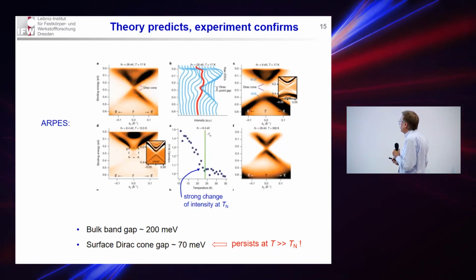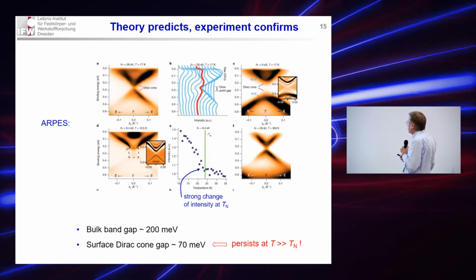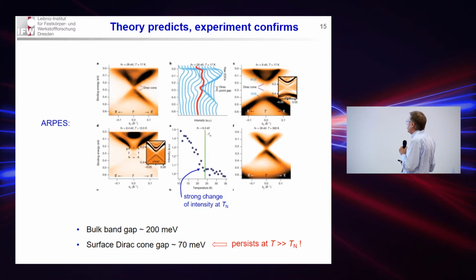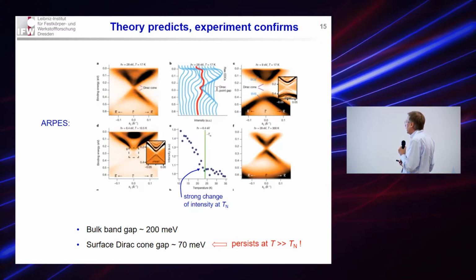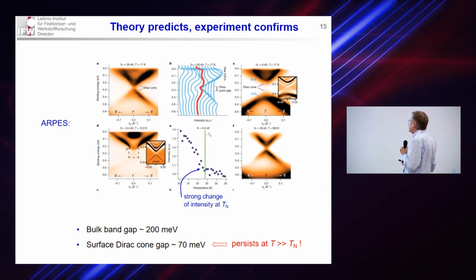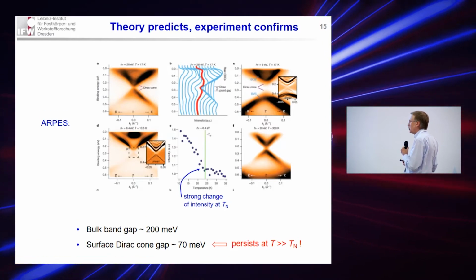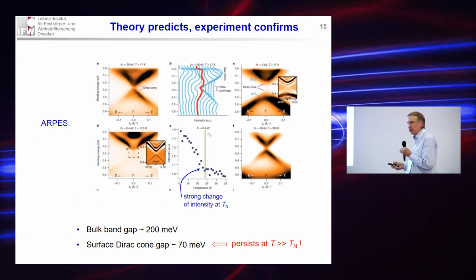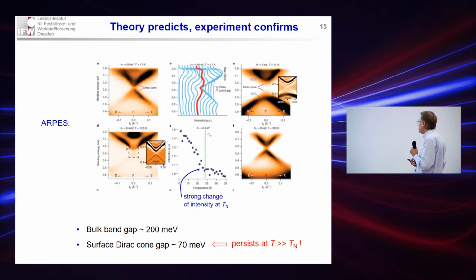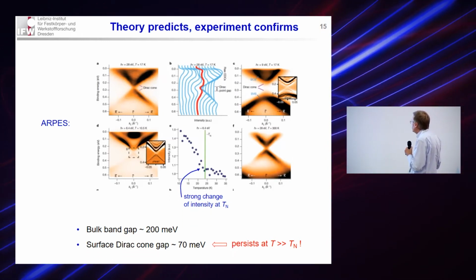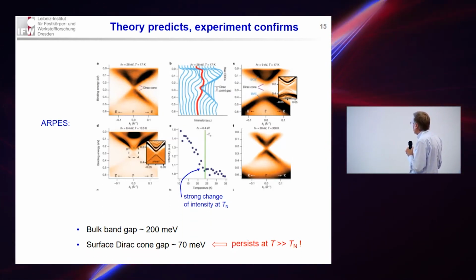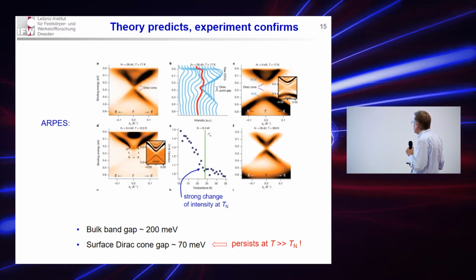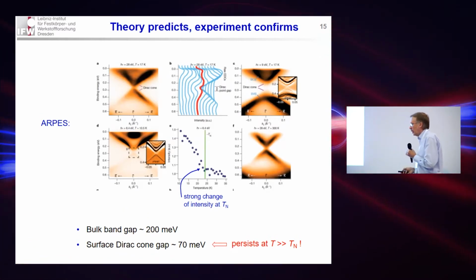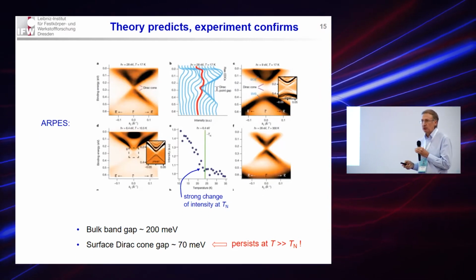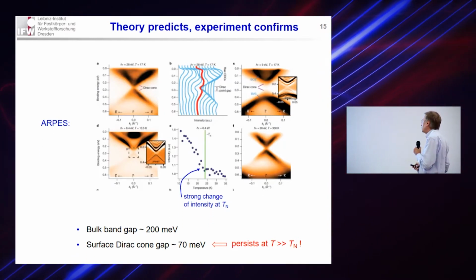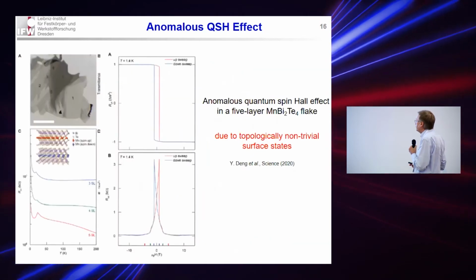Interestingly, the intensity of these Dirac cones drops significantly when approaching the ordering temperature from below. That means where the magnetic order is suppressed, one would expect this gap to completely disappear in the paramagnetic state, but it does not. It still shows some remnants of the gap in the k-space, a kind of pseudogap still present at temperatures much higher than TN. So that was a very unusual and unexpected behavior, which needs some explanation.